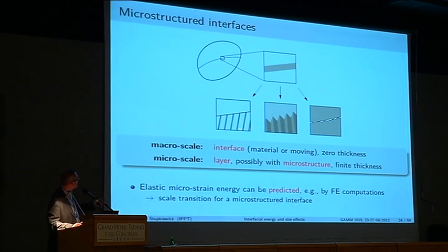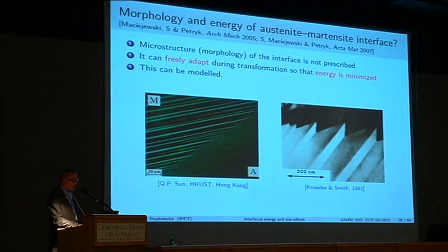And now if we look at these two, which are interesting for us for shape memory alloys, then we can see that the elastic energy here can be predicted, for instance, by finite element computations, and this corresponds to a kind of scale transition for the microstructured interface we have at hand. And that's what we will be doing soon. So if we now consider the austenite to martensite interface, we realize that the microstructure or morphology is not prescribed. It can deform, it can form freely, it can adapt to the conditions, and we expect that nature does it in the way that the energy is minimized. And this can be modeled.